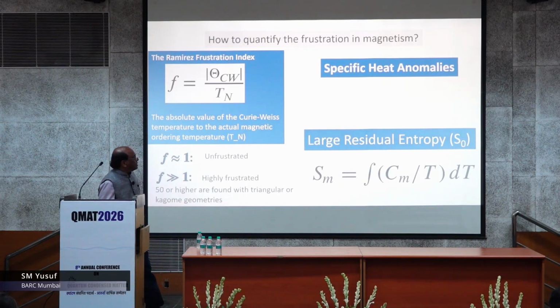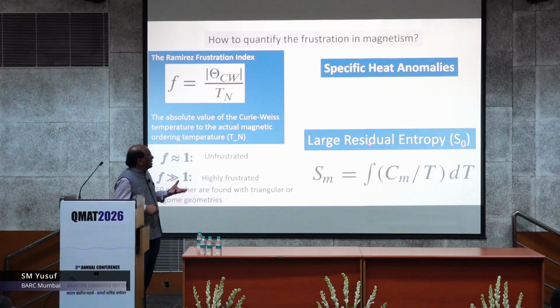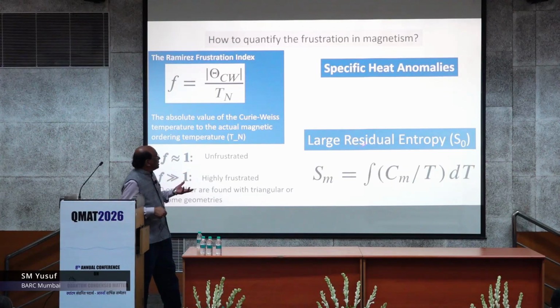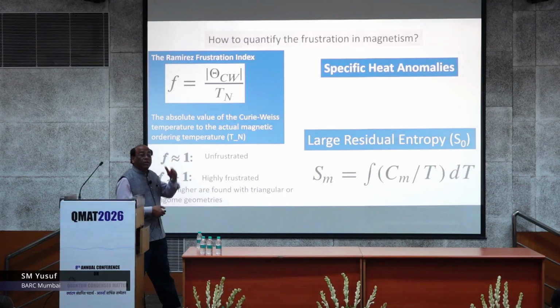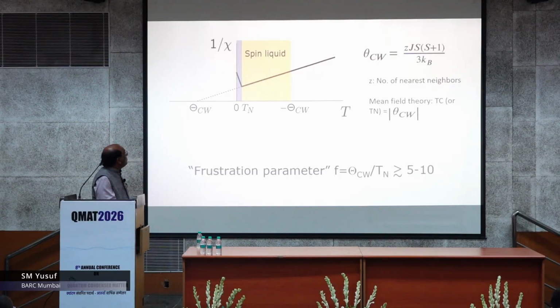How do we measure this entropy? This is the specific heat, this is temperature, and I will give some examples. There you will see that in a frustrated system a large amount of residual entropy remains even if you cool the specimen down to near absolute zero.